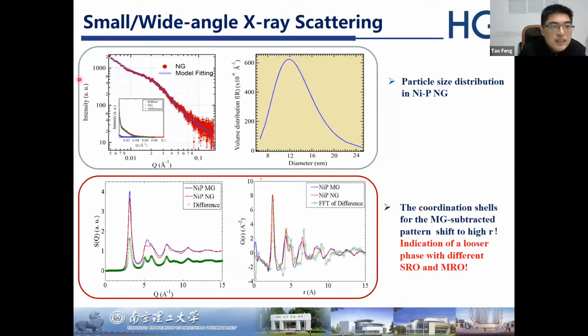We also used small angle and wide angle X-ray scattering techniques to get statistical information of the bulk material. From the SAXS data, we can get the particle size distribution in the nickel phosphorus nanoglass, which is around 12 nanometers. From the WAXS data, we can clearly see the red one is the nanoglass and the blue one is the metallic glass. We can see the difference in the S(Q) data, which indicates that the nanoglass and the metallic glass have different atomic structures.